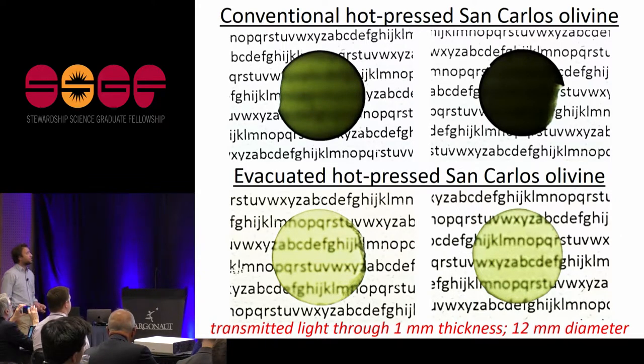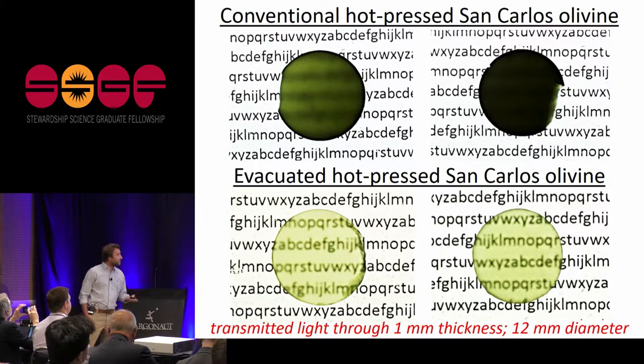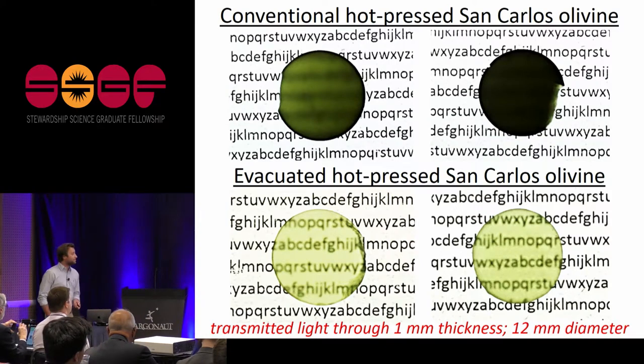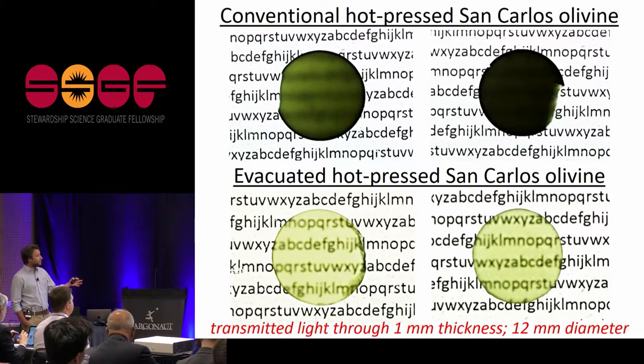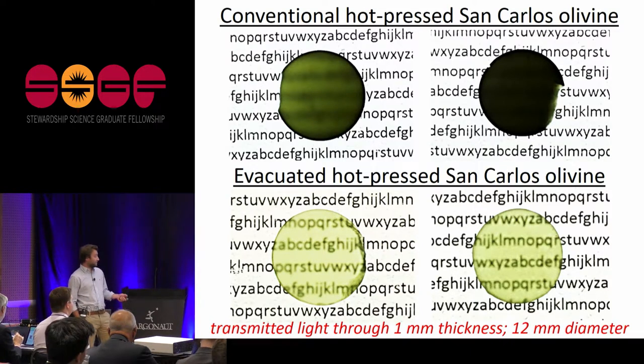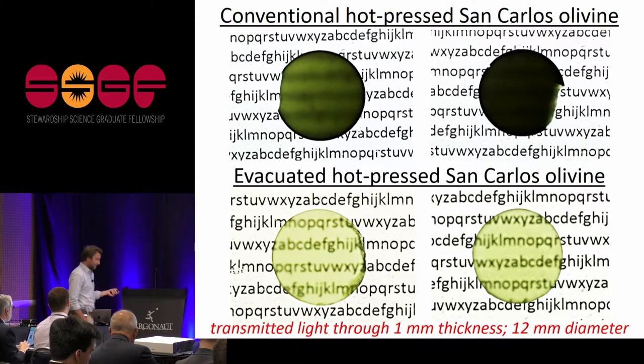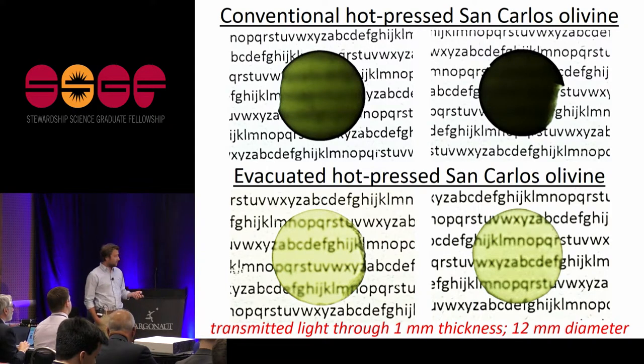This is a picture showing conventionally hot-pressed San Carlos olivine used in many highly cited research projects on mantle flow. My evacuated hot-pressed San Carlos olivine sits on top of text on transmitted light, showing you can easily read through a one-millimeter-thick slice — a macro-observable demonstrating we've achieved a much denser ceramic using this process.